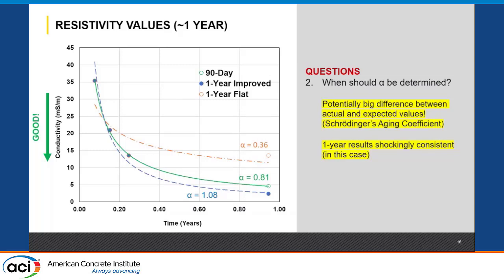So this is what happens. The green line is what is my conductivity if I just think that 90 days is correct. The blue is I measured it and it got better. And then the orange is I measured it and it flattened. And you can see there's a huge discrepancy here on what my alpha can be. So I'm calling this Schrödinger's Aging Coefficient. If I don't measure it, I don't know. If I measure it, could be better, could be worse, I don't know.